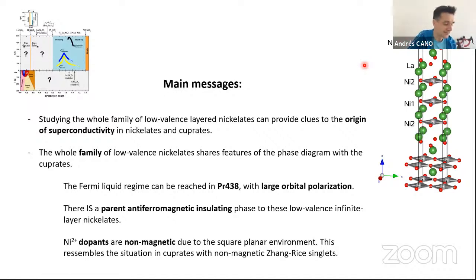My first question is about the 3-layer systems and the topotactic hydrogen. It has been suggested that in the infinite layer case, there is a difference between the lanthanum and the other systems. I think that you have not considered that. No. Because the system is quite big, but what is your feeling in the case of the 3 layers? Do you think that they are more robust with respect to the topotactic hydrogen? When you take the Ruddlesden-Popper phase and you reduce it, there is the risk that the hydrogens will sit at the apical sites. Do you have a feeling?